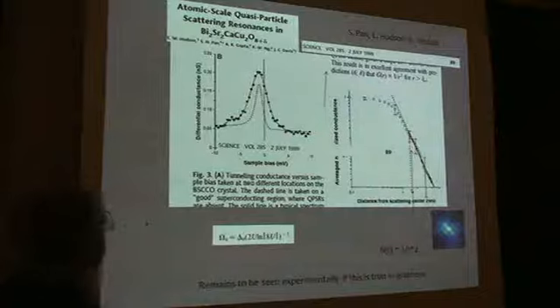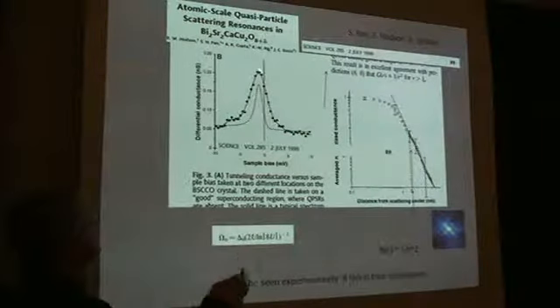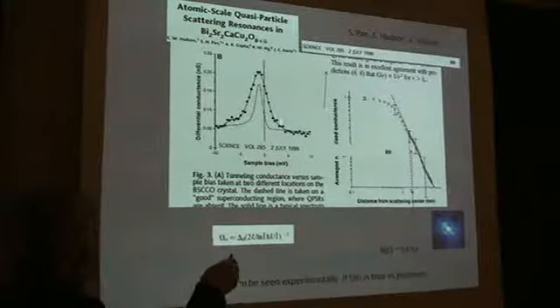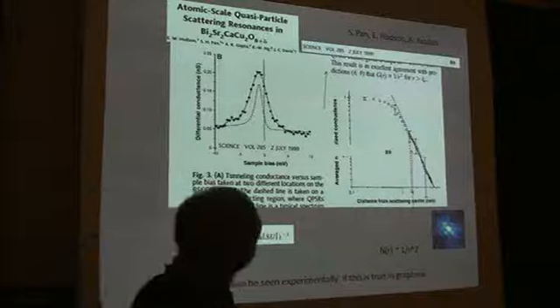And then with the same strength of parameter U, you can fit reasonably well the position of the peak and the width. So the dashed line here is the theory, the solid line is experiment. And you can see that if you fix the position of the resonance, within a factor of 3 you're getting the width.